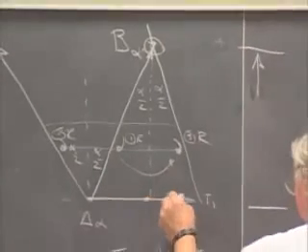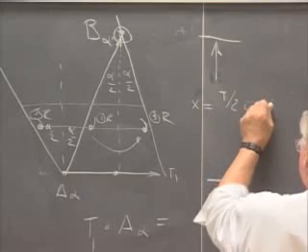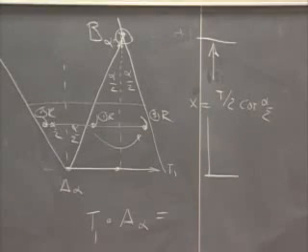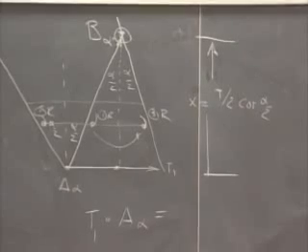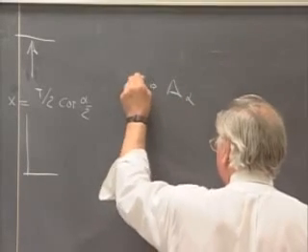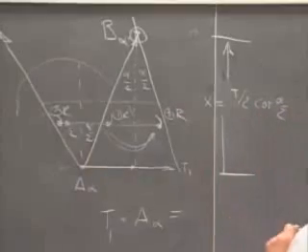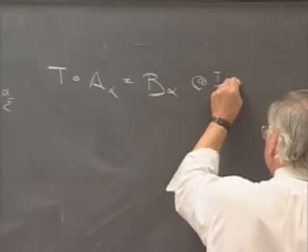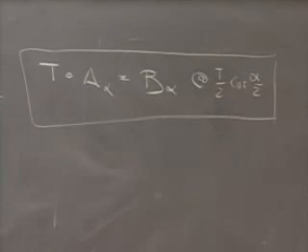It's going to be along the perpendicular bisector of the original translation, and it's going to be up a distance x, which is t over 2 times the cotangent of alpha over 2. So now we've got another, what I call combination theorems. And again, this is nothing more than knowing how to complete the product of two operations in establishing the group multiplication table. So let me write it down in the form of a combination theorem. This says that A alpha followed by a translation is another rotation in the same sense, both counterclockwise in this example, another rotation, B alpha in the same sense, about a point that is always t over 2 times the cotangent of alpha over 2 along the perpendicular bisector. So that's how you would go about making an entry in the group multiplication table.